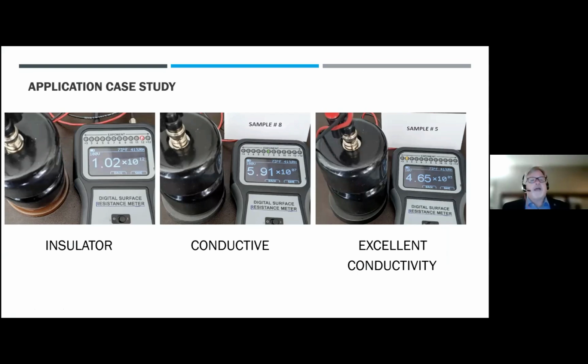The first slide, you could see it's 1.02 times 10 to the 12th. It's showing an insulator, not good conductivity. You could see something now down to 5.91 times 10 to the 8th, so you're getting some conductivity there on this sample. And then finally, in the last slide, you'll see where you're getting some really good conductivity, similar to what we were seeing in the previous slide with our 0.5% level of our additive in that composite.